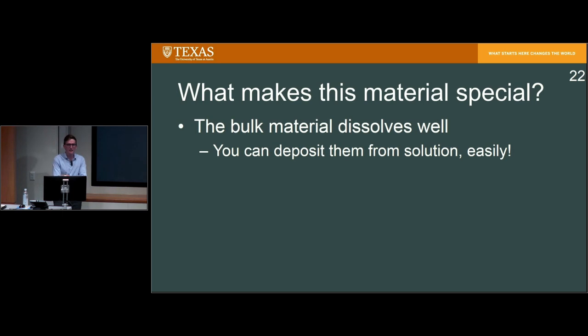Well, the first thing, that may appear trivial but is actually super non-trivial, is that the bulk material of perovskites can dissolve really easily. Think of the types of PV technology that you are familiar with: silicon, cadmium telluride, copper indium gallium selenide. These materials can't be dissolved unless you use incredibly difficult, corrosive, and really dangerous solvents. But methyl ammonium lead halides, formamidinium lead halides, all these perovskites can dissolve in very common lab solvents like dimethylformamide and dimethyl sulfoxide, which means that we can actually process bulk materials, not just nanomaterials, but bulk materials of these semiconductors from solution in a variety of different ways.